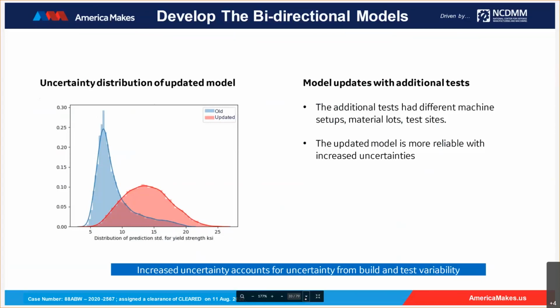The blue histogram is an indication of the old model, and the red histogram is an indication of the updated uncertainty. You can see that with additional testing results, the BHM uncertainty systematically increased. This is due to the introduced uncertainty from testing lab, like the testing site, material lot, and machine setup. By performing these experiments and additive builds at different locations and with additional uncertainties, the dataset itself has become larger with larger uncertainty, and our model can capture this increased uncertainty with a larger prediction error bar. Now the updated model is more reliable, with increased uncertainty to reflect that. So next slide, Neil, please.